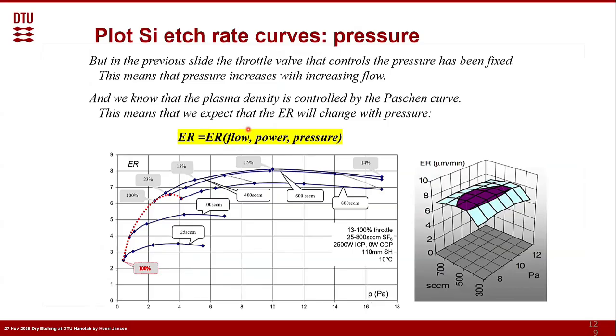But as you could see already a little bit, that has to do with the Paschen curve. It's not only the flow and the power that are responsible for the etch rate, because we also have to check the Paschen curve. When the pressure is very high, there will be a moment where the field cannot dissociate and ionize the plasma anymore, and then you also don't create the radicals. And at a very low pressure, it's the same. So again, your efficiency is compromised, and it will not work. That means that you can also find an optimum for the pressure.